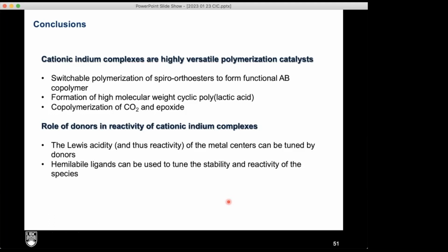So you can really have very fine tuning of the reactivity of these indium complexes by subtly changing the ligand design from an amine to an imine, for example, or by adding different solvents, or by tuning it by changing the hemilabile arms around it and really drastically tuning the reactivity of the catalyst.